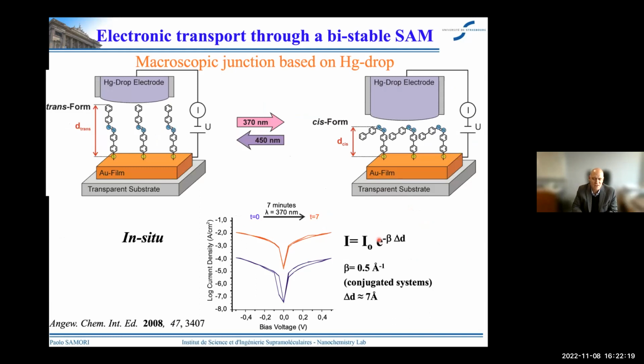As we were able to observe the isomerization in much larger domains, we decided to use as a counter electrode not anymore the tip of an AFM that has a diameter of a few tens of nanometers, but actually a liquid compliant mercury drop, which has a diameter of about 2 millimeters. And therefore, using a transparent substrate like quartz with an ultra thin gold film of 15-20 nanometers, we can shine light from the bottom and have in situ isomerization from the trans to the cis and vice versa, which is reflected in the IV characteristics shown here at the bottom.